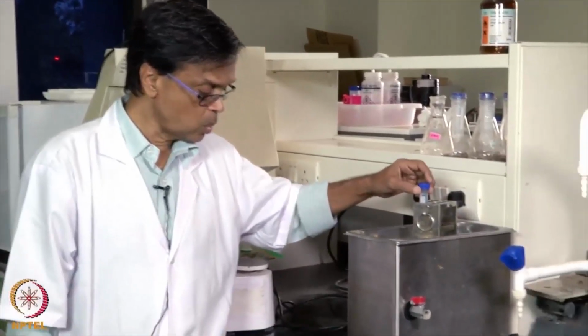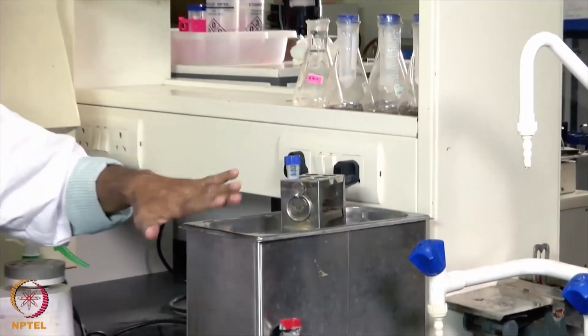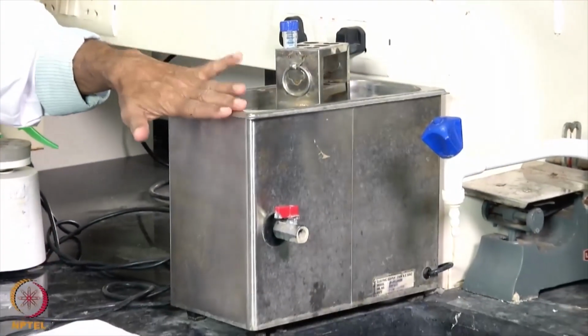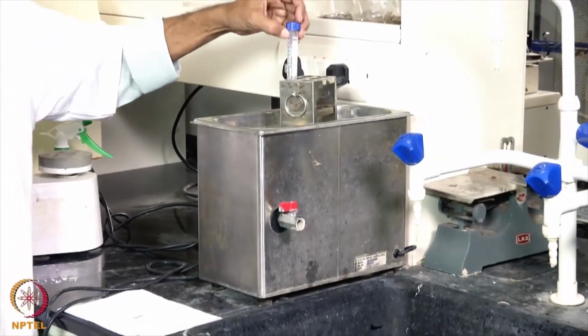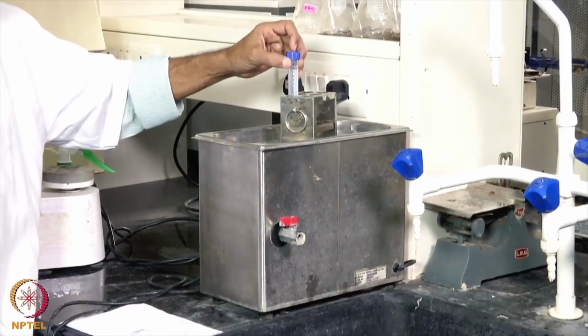This beta cyclic glucan is water soluble, whereas the beta linear glucan or curdlan is not water soluble. This glucan is water soluble, that is why we are using only 25%, and the 75% will be the carrageenan, and later on we will be cross linking with the glutaraldehyde. So initially we start with 4 ml water. Okay, this is a hot water bath, so we heat this water to 50 degrees centigrade.